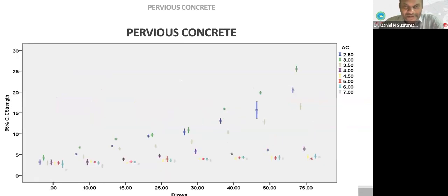If you look at this one, this is the same graph with the blows and aggregate to cement ratio, but the y-axis is giving us the compressive strength. So with lower aggregate to cement ratios, you can give a lot of compaction and your compressive strength exponentially increases, whereas any aggregate to cement ratio above 4 or above 3.5 is not producing any significant change in the compressive strength. So we found out that the optimum is not happening somewhere around 2.36, but somewhere between 3.5 and 4.